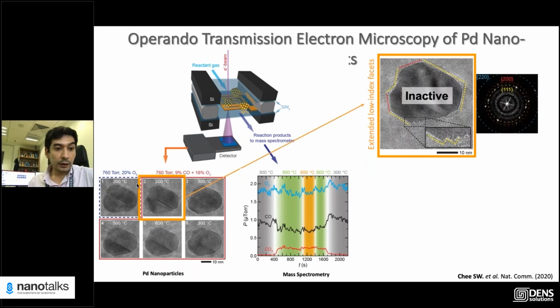Okay, so first when we introduced oxygen, at a low temperature, about 200 C, nothing happens. But then we start introducing CO. So the CO to oxygen ratio is 0.5 here. And what we see, the nanoparticle starts faceting up. It starts forming low index facets, so 111 and 200. And here, for example, at this corner, it even starts forming these edge facets, I mean staircase or sawtooth facets, that are 111.